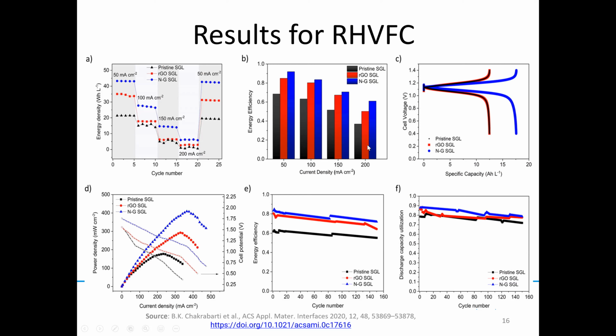Specific capacity is also better when we're using nitrogen doped graphene, so we can get much higher capacity. One of the main reasons for this is that nitrogen doped graphene improves the hydrophilicity, allowing the electrolytes to have better access to the electrodes and also to the membranes, and the overpotential is also less.